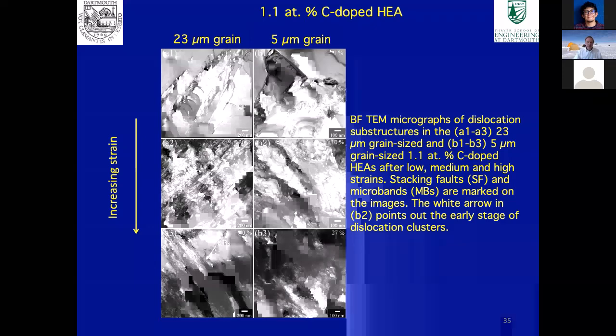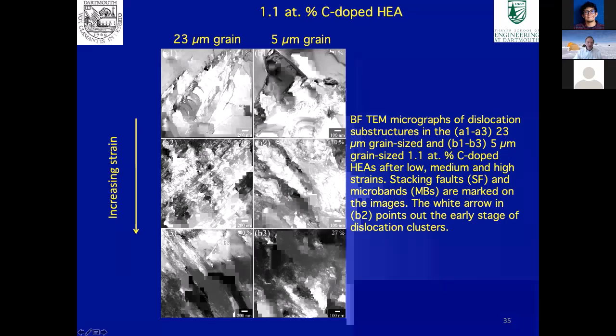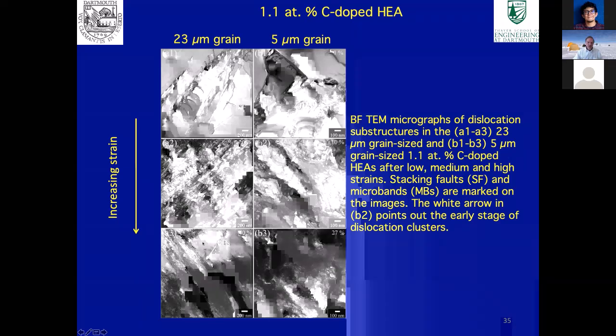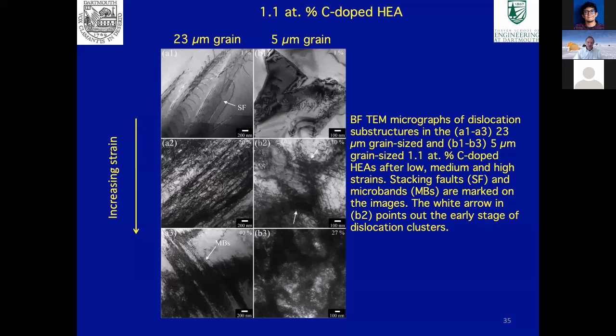In the high-entropy alloy, we did see one difference. For the larger grained material, we again saw dislocation structures exactly the same as in the as-cast material, where we got these microbands at high strains. But when we got down to 5 micron grain size, we no longer saw this microband structure in the material. So that's a slight difference as we get to very small grain sizes. So the grain boundaries must interfere with the microband formation in some way.